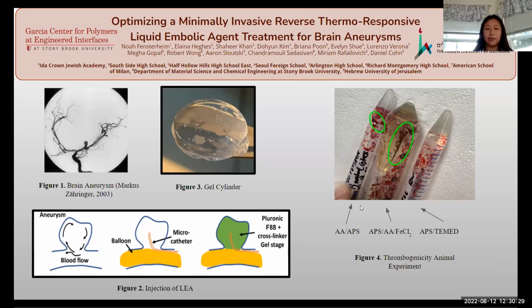In our first animal experiment, we tested blood clotting or thrombogenicity using 3 cross-linker combinations involving ammonium persulfate and various catalysts. The black spots that you see in the picture are blood clots, and the rightmost vial with the TEMED catalyst had no blood clots, meaning that it was not thrombogenic and the safest for us to use. We thus exclusively used the TEMED cross-linker in our ensuing experiments. In the second animal experiment, we successfully injected a gel of 1.25% TEMED and 99 milligrams per milliliter iohexol into a rabbit and are continuing to monitor it.